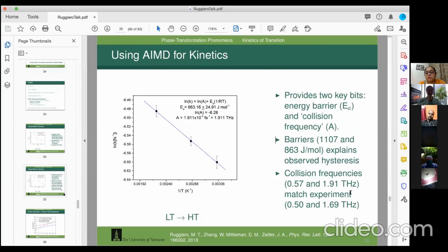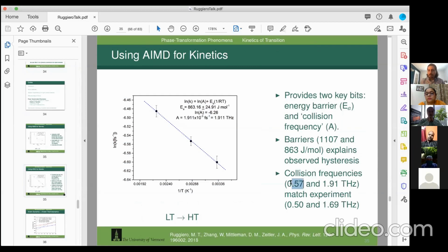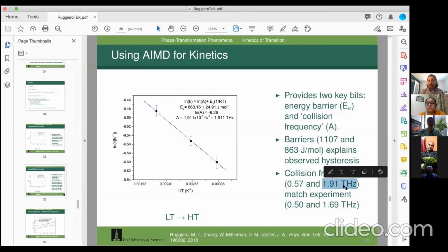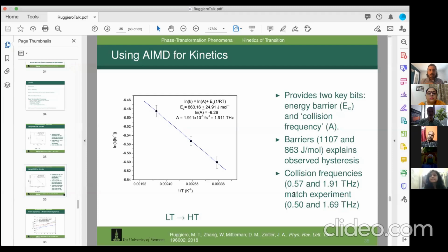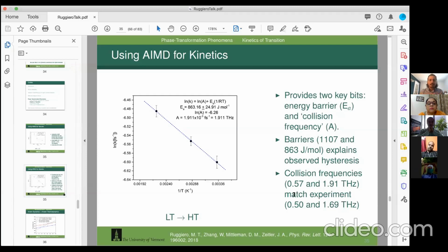And the other thing we watched was the peak shifts a lot more as a function of temperature than any other peak, which, as you can see, we're going from 0.5 to 1.9 terahertz. Most things maybe shift by 100 or 200 gigahertz. This shifts by 1.5 terahertz over the course of the phase transition. So those things together provide a lot of confidence that the terahertz mode is responsible.